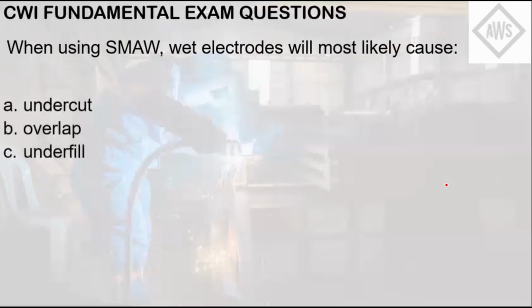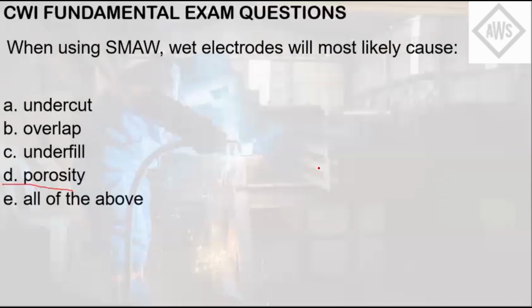When using SMAW, wet electrodes will most likely cause: letter A, undercut; letter B, overlap; letter C, underfill; letter D, porosity; letter E, all of the above. So the answer here is letter D. This is why electrodes shall be properly maintained at their appropriate oven temperature. Wet electrodes can cause moisture in the weld puddle and can cause porosity.